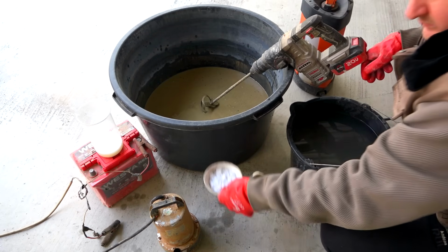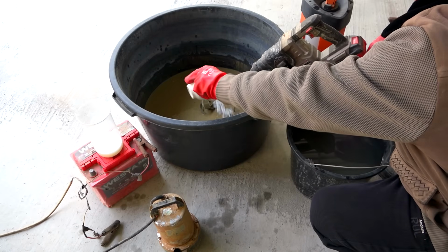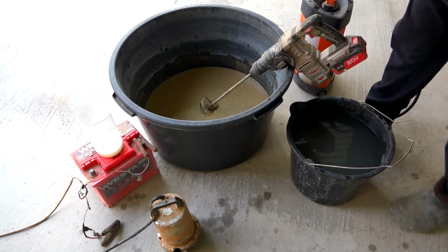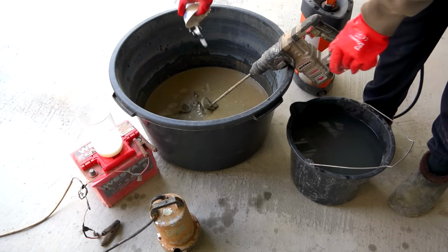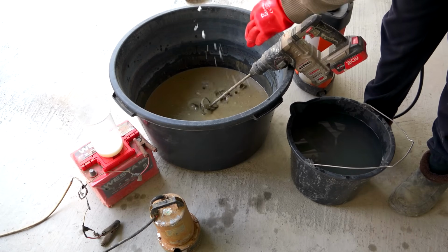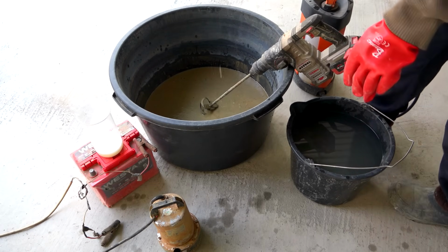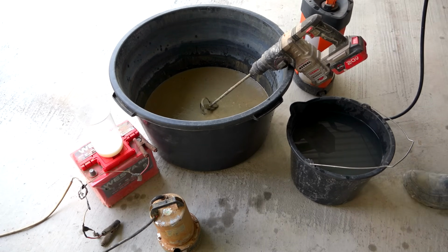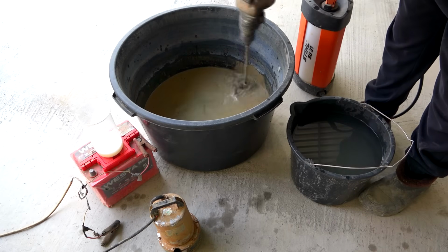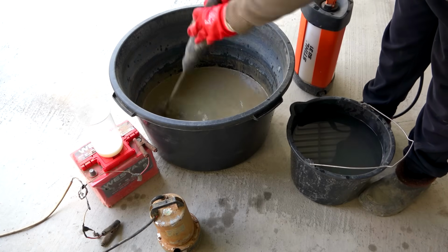The next day, I prepared everything I needed to use flotation and extract the remaining gold dust from the concentrate. This time, I'll use a different method, and I'll need a few simple things. First, I add simple chemicals to the pulp to stabilize the solution. The concentrate contains many heavy particles, which quickly compact and settle to the bottom in a dense layer.